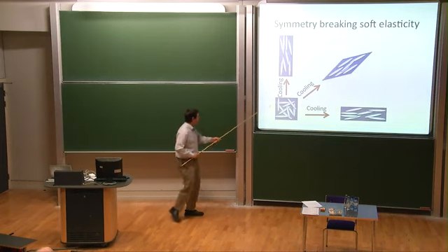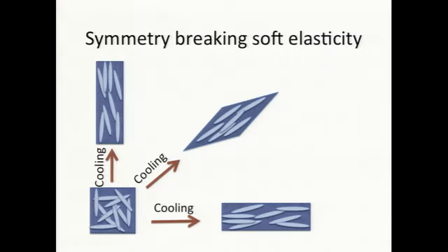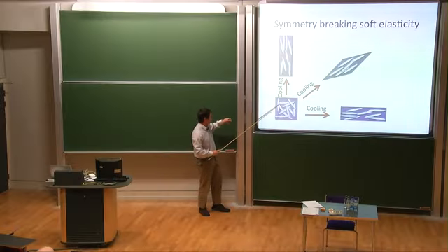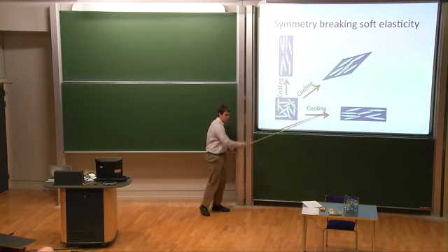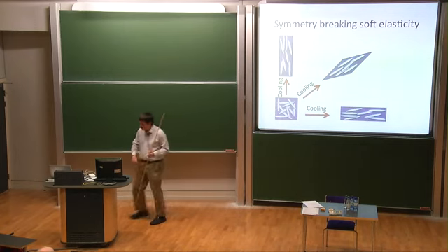Also, though, we've written the energy in some sense in a counterintuitive way, because we've written the energy as if we cross-linked in a state like this. And so if you imagine deforming this state, although we know going round this circle ought to be soft, it's only when we write with respect to this state that we get to really see that symmetry obviously. So what we're going to try and do then is, rather than write with respect to deformations from this cross-linking state, return back to the isotropic state and write our deformations with respect to that state. And what we hope we're going to see is that when we do that, suddenly this symmetry structure becomes obvious and the soft mode appears.